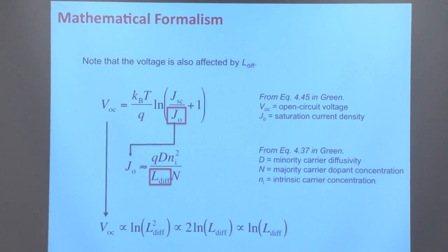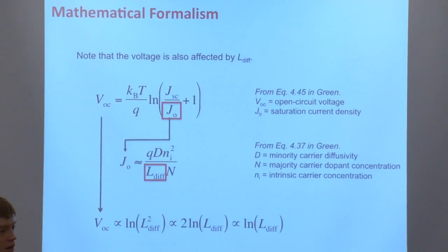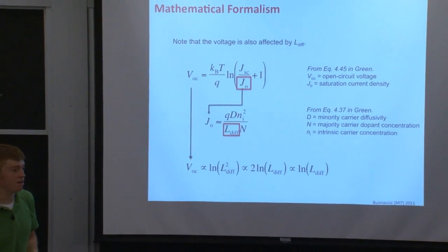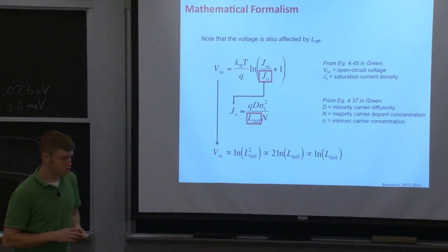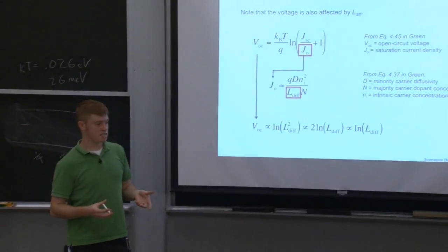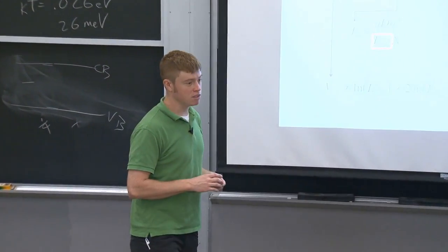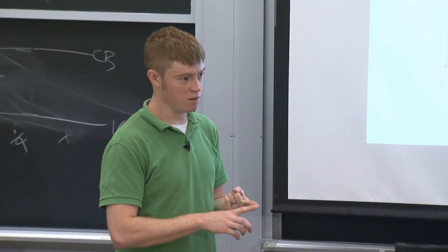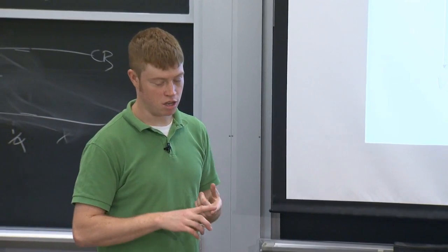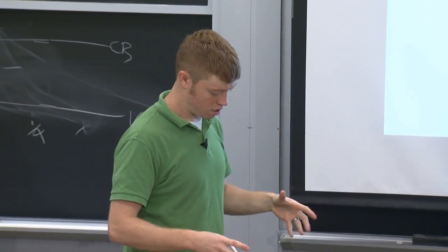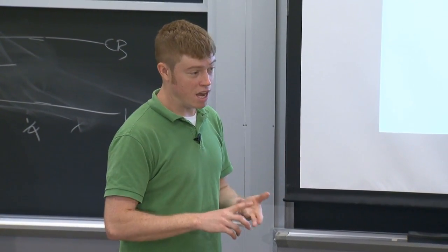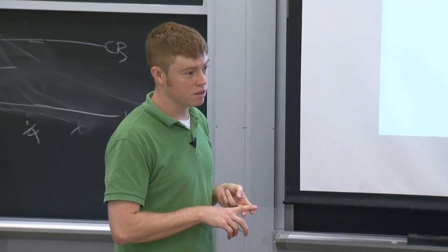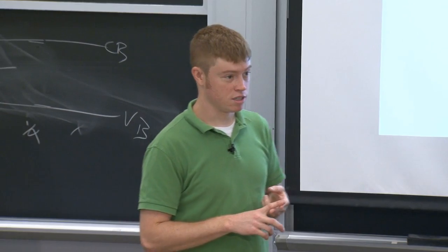And so for most types of cells, heat is very, very bad, especially for crystalline silicon. For amorphous silicon, that's different, but I'm not going to get into that today. For crystalline silicon, heat is generally very bad for the performance. And when you do testing, for example, when NREL does testing, they'll rate all your cells at AM 1.5G, some calibrated solar simulator that's illuminating your sample, and they're kept at constant temperature. So the temperature is always reported, and it's generally kept at 25 C. So the temperature is a very important characteristic.